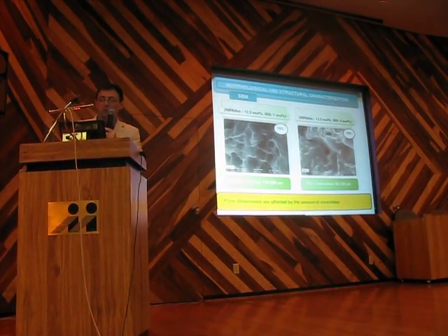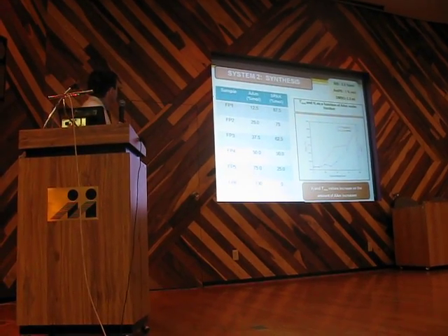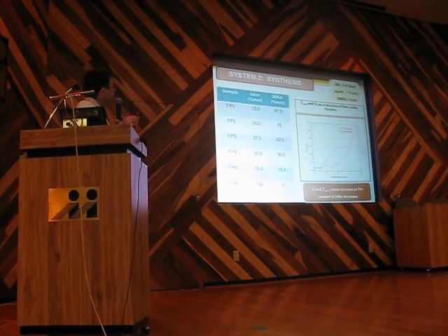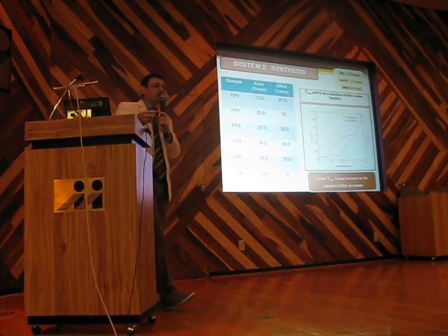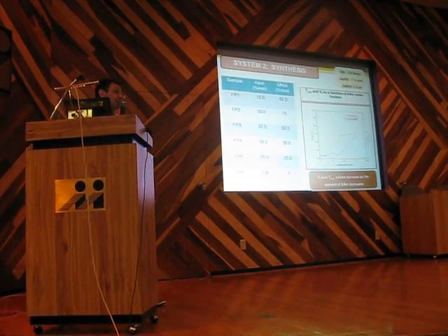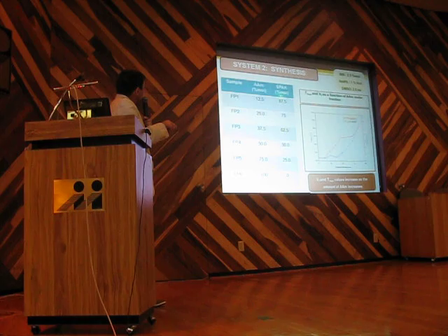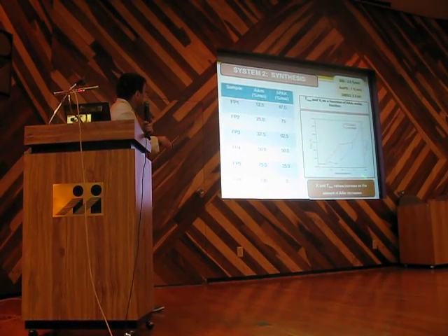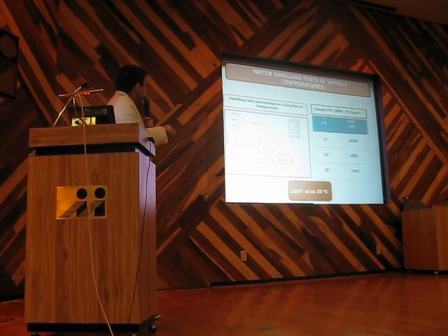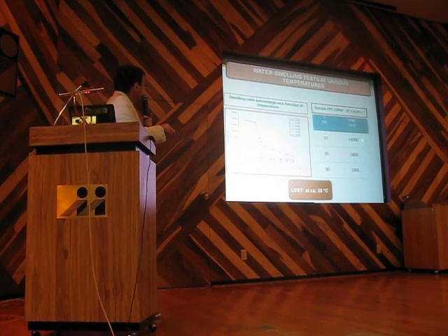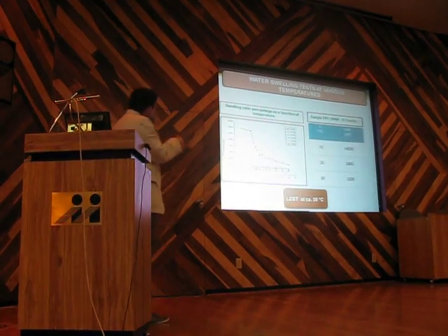Okay, I can go a little bit faster. Now, let's remove NIPAM completely and use acrylamide. We copolymerize acrylamide with SPAK in these ratios, and what I would like to tell you is just that even in this case, we found a very high swelling ratio, up to 14,000 here.